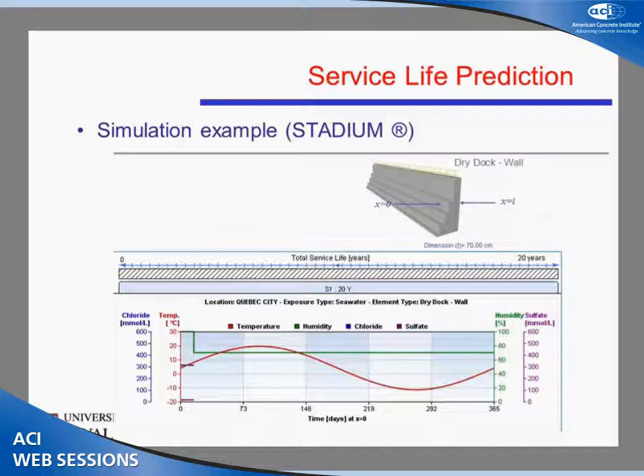You can see here that this structure is saturated on one of the surfaces for a short period of time. As a matter of fact, there's a chloride content here. So it's completely submerged for part of the year. And then for the rest of the year, it's actually dried at humidity about 70%, which is normal for Quebec City. So that's how we design our simulation.